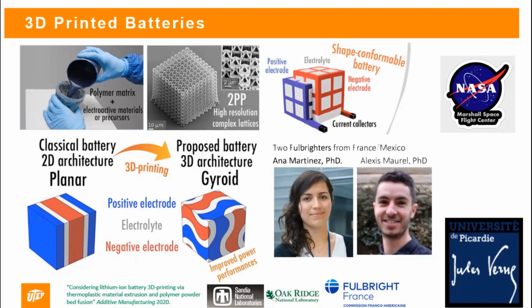What we've been using so far is photopolymerization. And now we're getting that 2-photon system to get the best resolution. And those aren't inherently good at multi-material printing. I did show a spiral in red and a pillar in clear. But the idea is that we would dissolve in precursor salts and then print 3 materials and then do a thermal post process that would burn out the plastic and cause a chemical synthesis to the chemistry that we needed in multi-material.